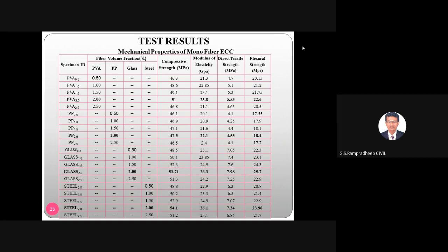For that, a slight difference is getting. But we can't observe, as I already pointed out, the variation in the compressive strength, whereas you can observe the variation in the tensile strength. Some of the readings are coming around 4.25, and some of the readings around 7. A major deviation of 3 MPa is coming, right?